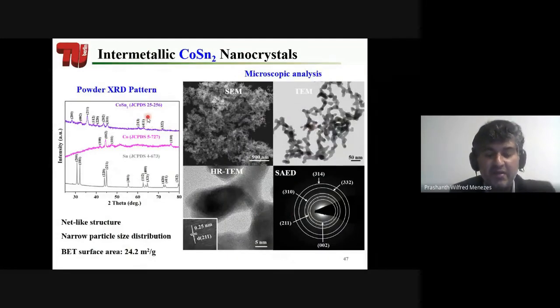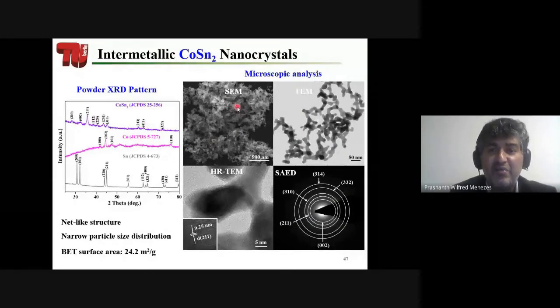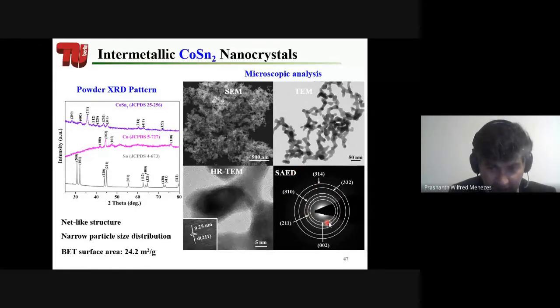This is the XRD pattern I want to show you. This is just to show that what we made is a pure phase. This is the scanning electron microscopy. From transmission electron microscopy, we could see that there are very small nanoparticles. This is the high resolution. You see that they are almost 5 to 10 nanometer particles. This is the selected area diffraction pattern.